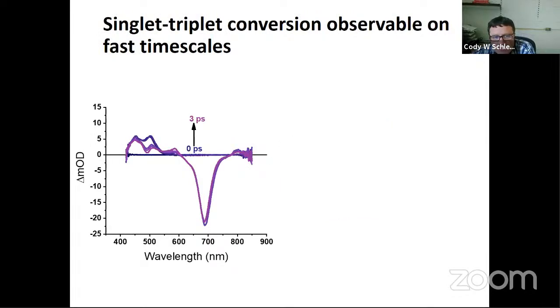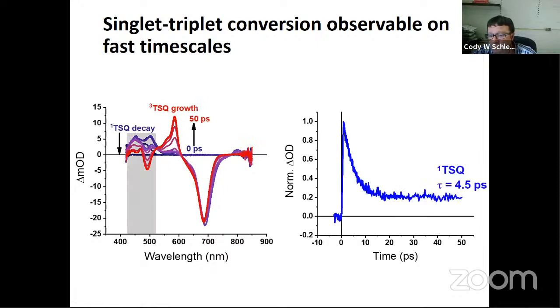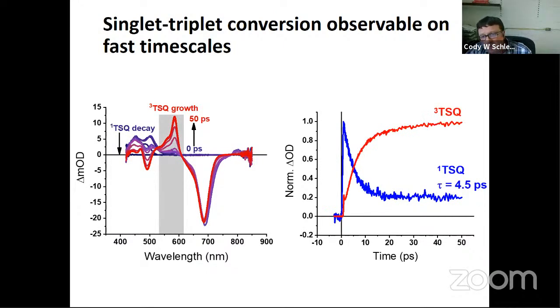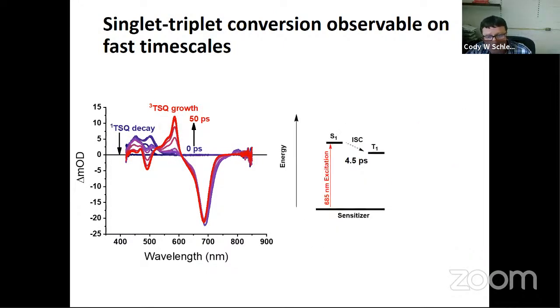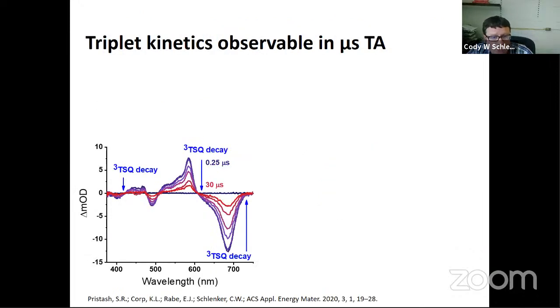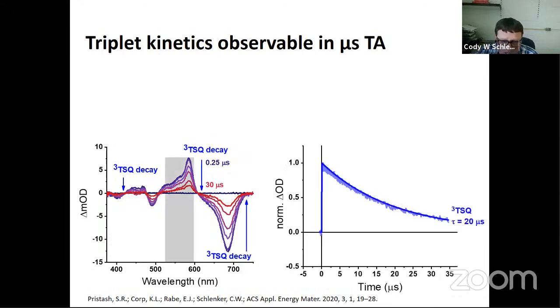Here we can monitor the drop in the singlet absorption and the introduction of the triplet of this TSQ molecule, and we can monitor the time scale for that. It's about 4.5 picoseconds. That's pretty good for having no platinum or iridium around. And so we can see the growth of the triplet there, so we can monitor the kinetics for that. We can also monitor the kinetics for the triplet of our excited state, and we can see that lasts for about 20 microseconds. So this is the decay of the triplet of our excited state here.